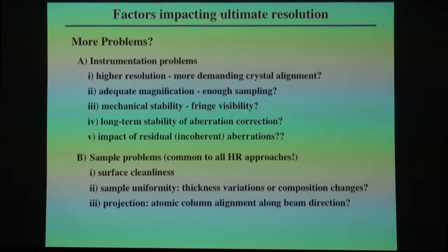Okay, so we have some other factors that are impacting ultimate resolution. Higher resolution demands more accurate crystal alignment. Do we have enough magnification to sample all of the higher resolution detail? The mechanical stability has to be even better. Maybe you can test that with lattice fringes. There are also issues with all of the aberration correctors that are so far being manufactured. They do not maintain the aberration correction for very long. You have to go back. Just because you check it at the beginning of the morning doesn't mean it's going to be well corrected even half an hour later. Some cases, depending on the microscope, you may have to adjust the aberrations every 10 minutes or so, or every 2 minutes or so. And you have to worry about the impact of what we call the residual incoherent aberrations.